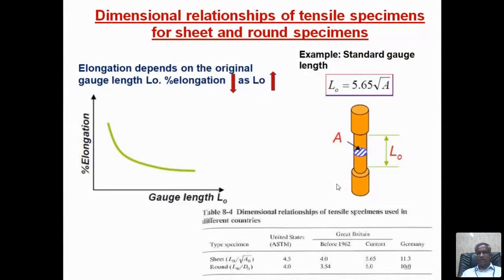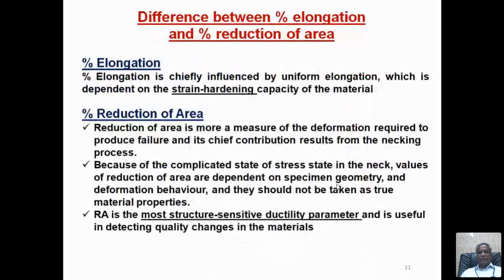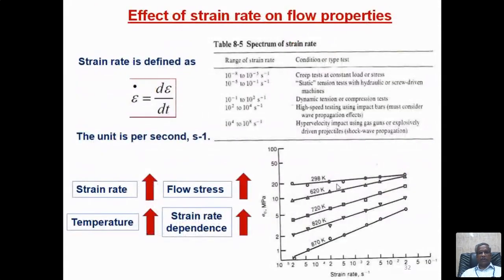So you have to use this relationship, 5.65 square root of A. The cross-sectional area you can find out, pi by 4 D square is the cross-sectional area. Substitute in the equation, and whatever value comes, you should maintain as the gauge length, okay? And the difference between elongation and reduction in area: reduction in area is a structure sensitive property, a ductility parameter, but elongation depends on the strain hardening capacity of the material. Both are for ductility measurement.